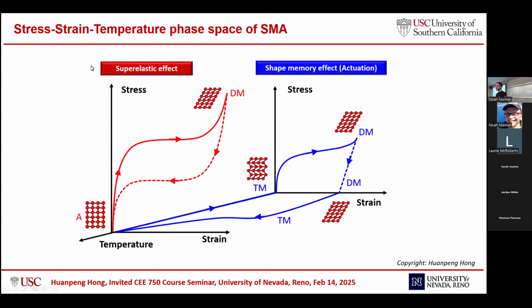So here is the stress-strain-temperature phase space of the shape memory alloy in a 3D space. Normally for conventional metals such as steel and aluminum, we only care about stress and strain. When the temperature changes, the yield stress and ultimate stress will also change, but it's not as significant as in the shape memory alloy. As we can see, this axis is the temperature axis. At different temperatures, the material will exhibit totally different phases and totally different mechanical behavior. So the special thermomechanical behavior allows so many possibilities for this material.